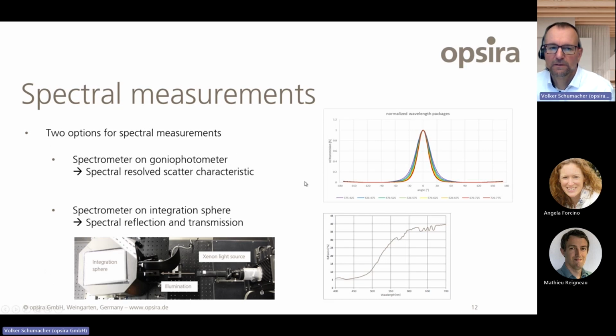Also, I want to mention some words on spectral measurements. We have two options for spectral measurements. There we can mount the spectrometer to the goniometer, and then we get the spectrally resolved scatter characteristic. Here we can see a result of a volume scatter material measured at different wavelengths. We see the bluish curves, they belong to short wavelengths. They are scattered more than the longer wavelengths here, the reddish curves, which have a lower scatter characteristic, a smaller full width half maximum. This is a result of the spectrometer on the goniophotometer.